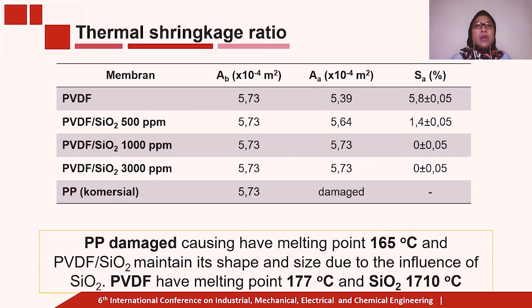The PVDF nanofiber membrane separator thermal shrinkage is around 5.8%, and PVDF with SiO2 500 ppm is 1.4%. Shrinkage that occurs in PVDF is small so that it will remain safe despite minor disruption due to the shrinkage.